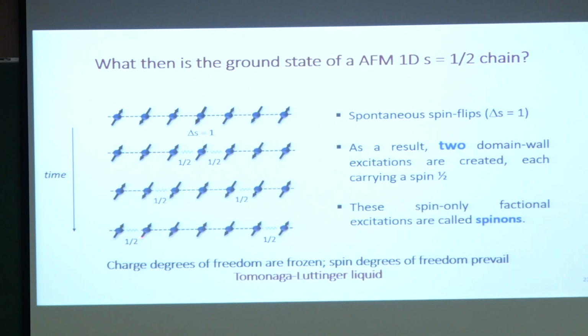So therefore you have these domain wall like excitations. These are called spinons. In an antiferromagnetic chain, if you think about its ground state, the ground state is quasi long range ordered, which means that you have long regions where there is antiferromagnetic ordering, but then suddenly there will be a spin flip, not because of temperature but because of quantum fluctuations.